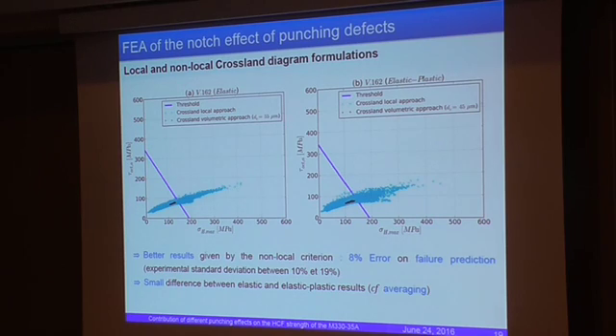Using a local approach, we get very conservative results. So we had to use a volumetric approach in order to average values on the volume around each integration point. And we are able to predict the danger coefficient for critical defects. So we are able to estimate with about 8% error if we will get fatigue initiation on the crack or not. And due to the averaging, we didn't find any significant difference between elastic and elastoplastic hypotheses in our calculation. So let's move to the conclusions and prospects.